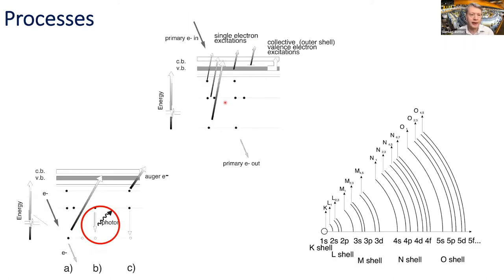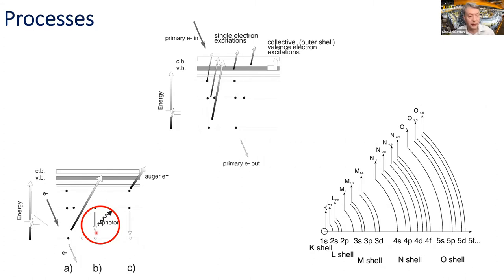Looking at excitation processes: a primary incident electron excites electrons from core levels or from the valence band to unoccupied states. These can come out as secondary electrons. We measure primary electrons that have passed through and record the energy they lost — through generation of photons or electrons. Instead of incident electrons, in X-ray absorption you have photons. The nomenclature of ionization edges is the same as in X-ray absorption, depending on the core level involved.